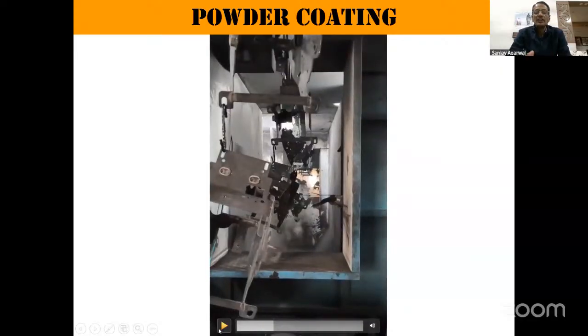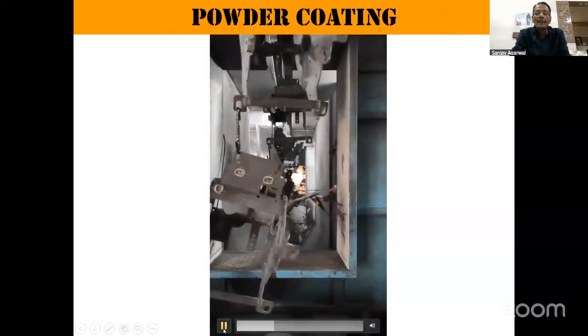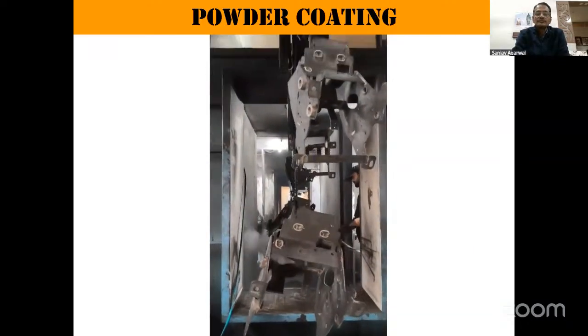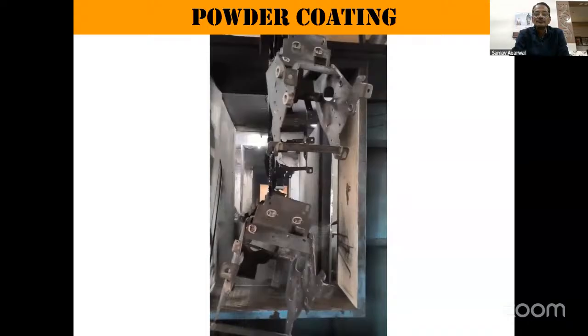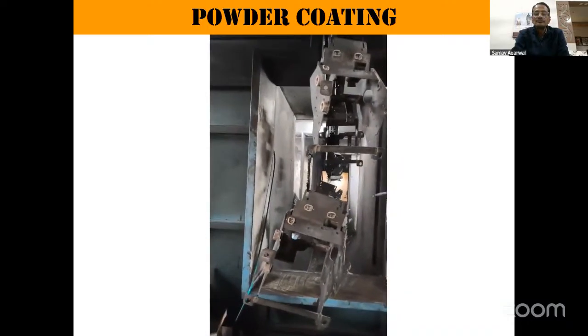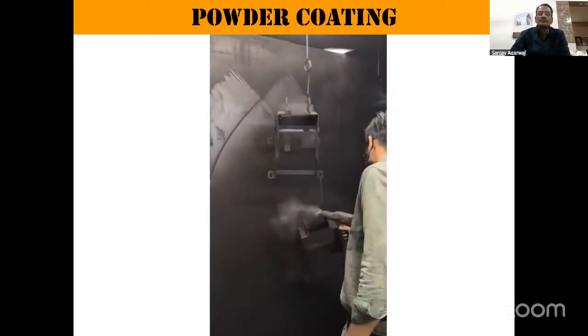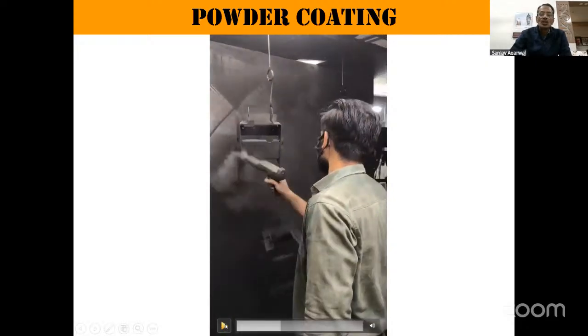Parts are entering the powder coating booth. The powder spray is a highly skilled job because the thickness of the paint required is 80 to 120 microns. These operators are trained in how many times they have to spray the powder to maintain the thickness of the paint. It is called DFT.